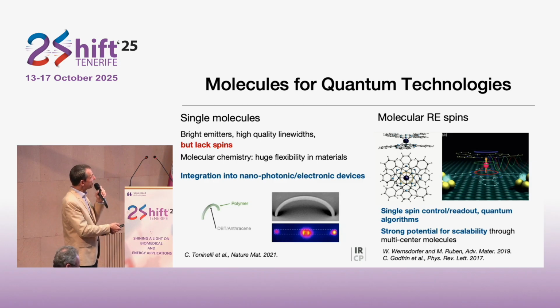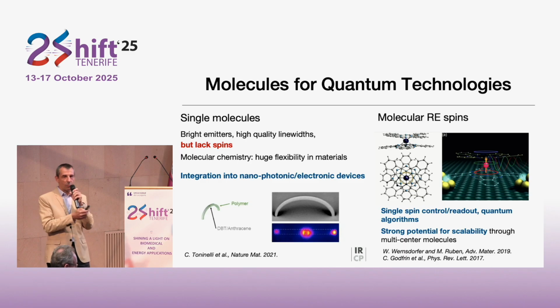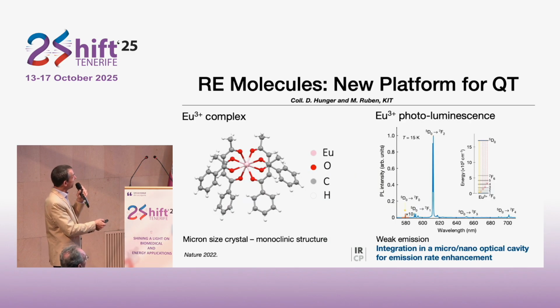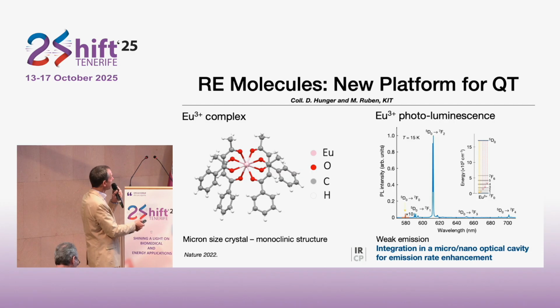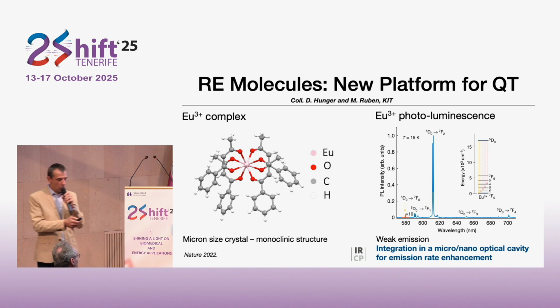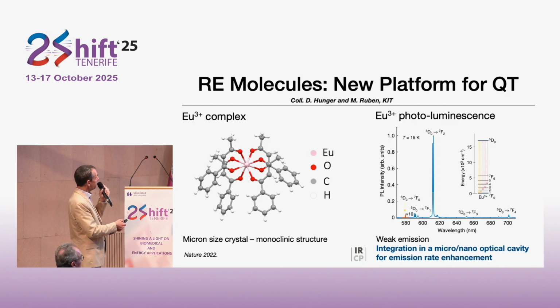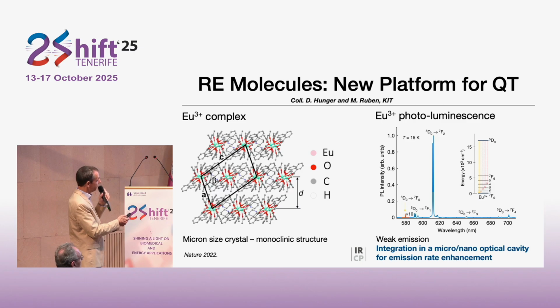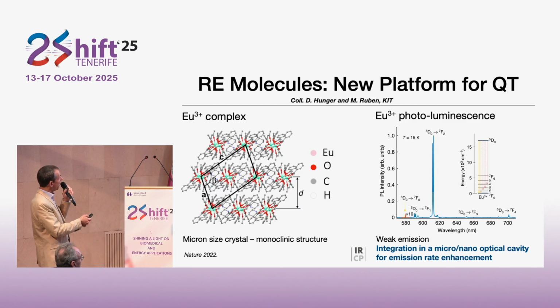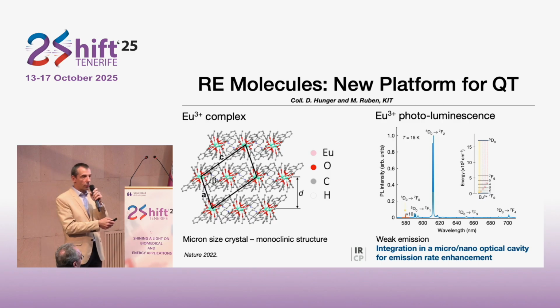So starting from these potentially very promising systems, we thought, okay, but what happens to the optical transition? And after a few trials, we ended up with this particular molecule complex where you have the europium ion in the center and then you have 4 ligands around. This molecule was crystallized in a monoclinic structure and used as a powder, essentially. Okay, so here you have a picture of the crystallized structure. It is a layered structure. Note that the molecule itself, what I just showed, is charged, so you also have a counter cation in the structure.